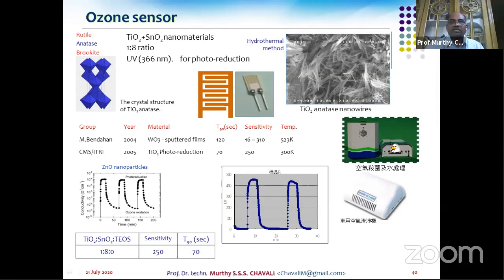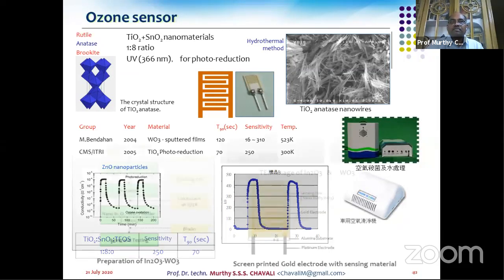Another sensor we tried is with SnO2, tin oxide, and titanium oxide. We could not get the proper results. Proper results in the sense we got results, but these were not accepted by the industry. So we combined TiO2 anatase type material and SnO2 in a 1:8 ratio. Different ratios have been studied, but finally we ended up with a very good sensitivity of 250 and a T90 of less than 70 seconds. This has been prepared and commercialized earlier. So this is another type of ozone sensor that we have developed in our laboratory.